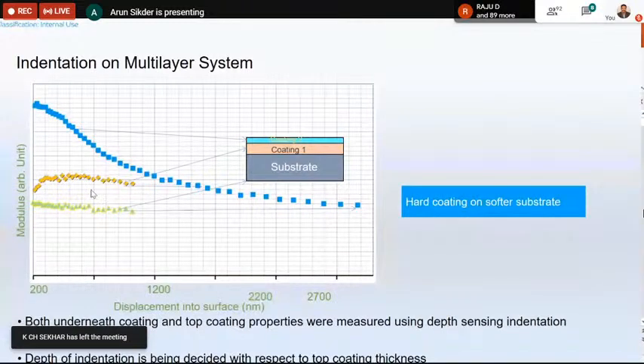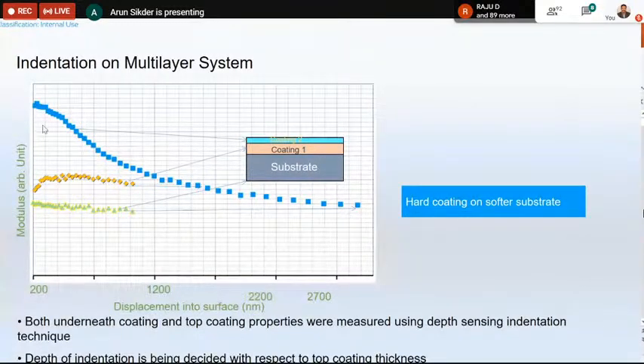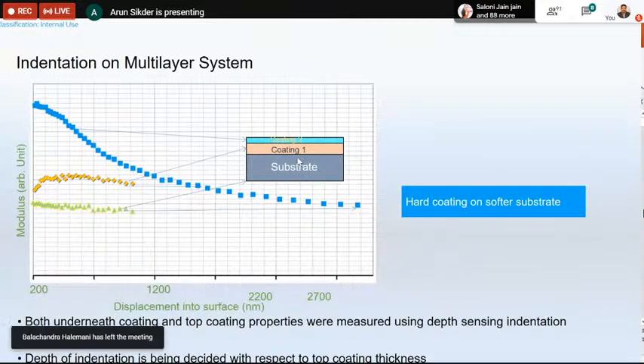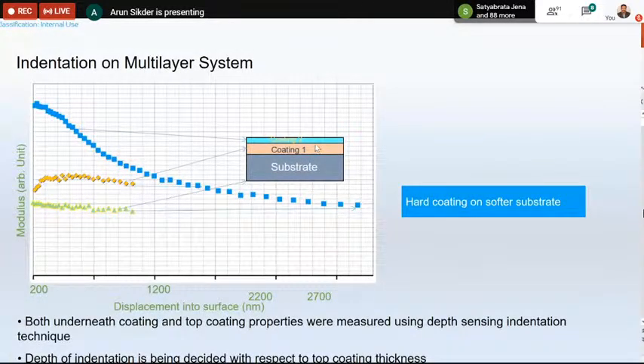So from one indentation on this multi-layer, I know this is my top layer, coating one, coating two. When it goes down here, it is my one property. And when it goes down here, I can take my substrate properties. So without testing three different materials separately, I can do one test and then assess their properties. I need to know the thickness of those coatings. So that's a powerful technique to assess multi-layers. Many times we cannot access the substrate separately, or the intermediate coating. So we need to do a test and then get the coating properties.